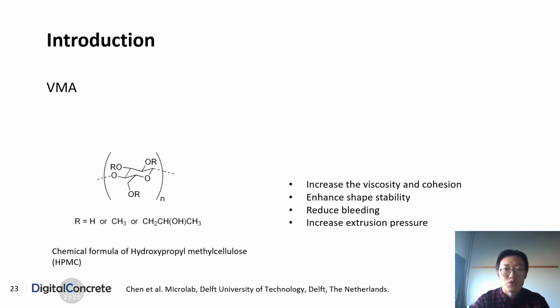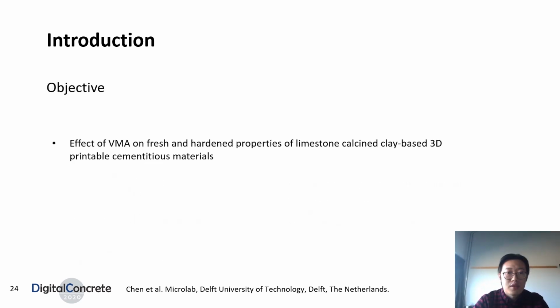It could help to increase the viscosity and cohesion of the fresh mixture, which showed sufficient stiffness for extrusion. But using a slightly higher dosage of VMA could increase the extrusion pressure significantly. Therefore, our objective is to investigate the effect of VMA on fresh and hardened properties of limestone calcined clay-based 3D printable cementitious materials, and eventually to find out the optimal dosage of VMA.